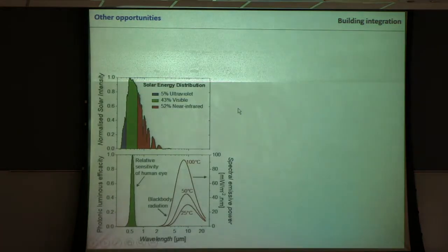So the smart window market is really massive. So how can we actually use our mirrors? What we have to know here is that it's not only that we have to manage the near infrared, but especially in colder countries where you want to keep heat in, you also have to manipulate the black body irradiation. So what we thought is we can use commercially available low E glass. They have just a transparent oxide layer that reflects in the further infrared. And on one side, a DBR of ours that reflects in the near infrared. So here you would have our mid-infrared low E mirror glass that you can buy.